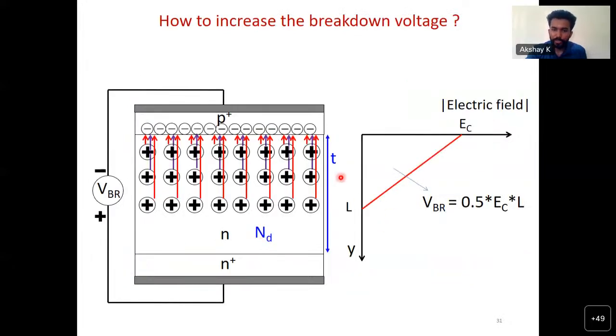When you reduce the doping, what happens is that this slope is there, right? So this slope, if you reduce the doping, the slope will also be lower. That means the electric field will decay down slowly. You have a higher area under the curve, right? And an area under the curve is nothing but the breakdown voltage. So if you reduce the doping, you have a higher breakdown voltage.